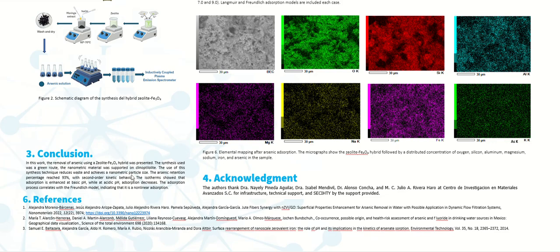Conclusion. In this work, the removal of arsenic using a zeolite iron oxide hybrid was presented. The synthesis used was a green route, the nanometric material was supported on clean clinoptilolite. The use of this synthesis technique reduces waste and achieves a nanometric particle size. The arsenic retention percentage observed was 93%, with second-order kinetic behavior. The isotherms showed that adsorption is enhanced at basic pH, while at acidic pH, adsorption decreases. The adsorption process correlates with the Freundlich model, indicating that it is a nonlinear adsorption.